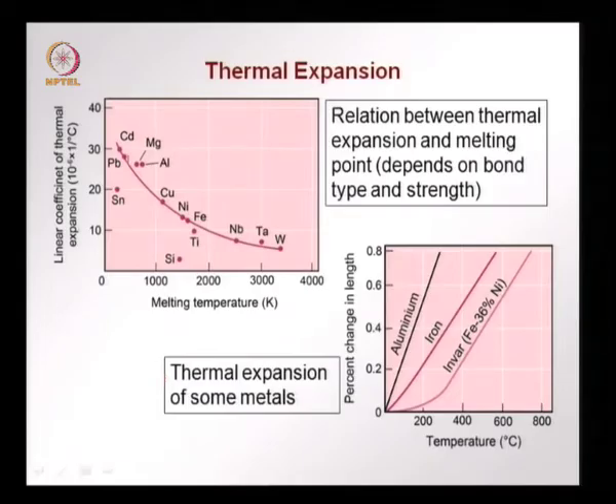We have different metals, and on the x axis we have the melting temperature. So, higher melting temperature indicates a higher bond strength. On the y axis we have the coefficient of thermal expansion, and again a higher bond strength would mean that the coefficient of expansion is lower, and you see a range of metals which fall on this line. So, clearly we see that as the melting temperature increases due to the higher bond strength, we have a lower thermal expansion.